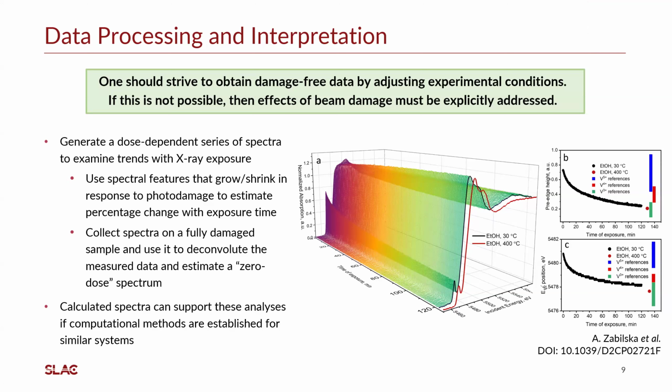Yeah, I agree to an extent. However, this would then just indicate that you can never be quantitative with this sort of thing. It's always going to be qualitative because, for instance, if you're applying this sort of method to ligand K-edge X-ray absorption and you're trying to quantify the covalency in the pre-edges, then if you're just estimating this, the values that you get from that peak area are never going to be quite accurate because, as you said, it'll just be an approximation.